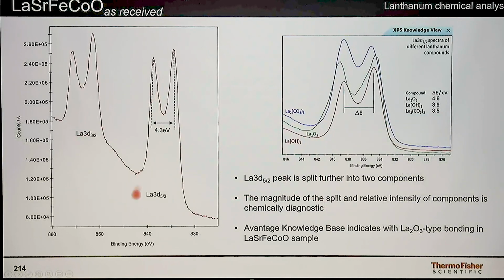And if we look at the lanthanum chemistry, we should only have 2 peaks for a 3D transition, but due to quantum effects from the number of electrons that lanthanum has, we see the doublet split into a multiplet, and so we have 2 peaks for each component of the doublet. But the splitting of them is quite diagnostic of the chemical state, so the distance between these 2 peaks, depending on the type of compound you have, gives you a different value. And so here we're looking at something that's got lanthanum 3 plus oxidation state.